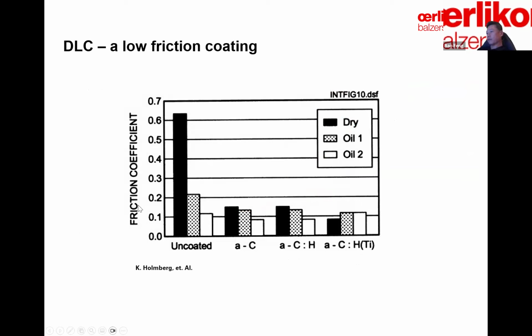Another special property of this coating is low friction. This is an early study by Kenneth Holmberg, the author of the coating tribology textbook. He was trying to compare DLC coated steel against uncoated steel in a sliding reciprocating linear tribometer test, also under different lubrication conditions: dry versus oil 1, which I believe is a mineral oil, and oil 2, which is hydraulic oil with EP additives.